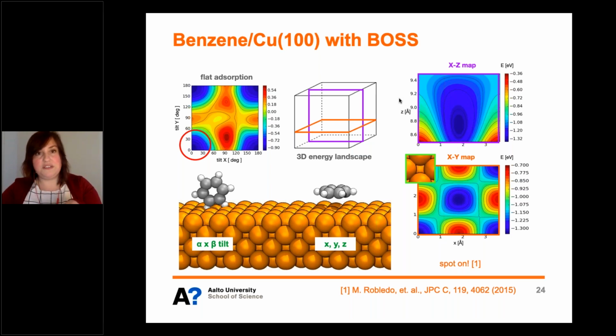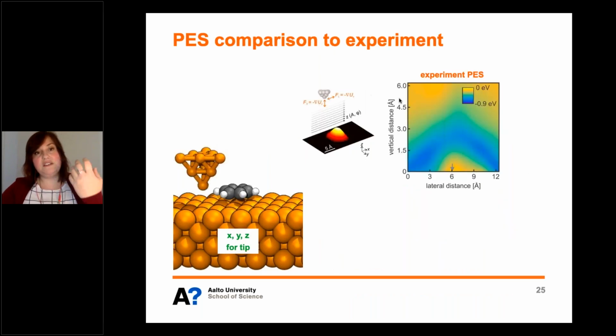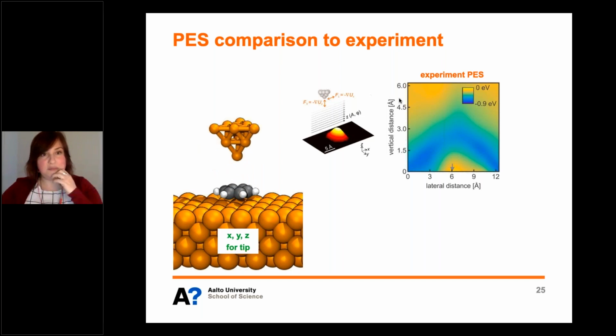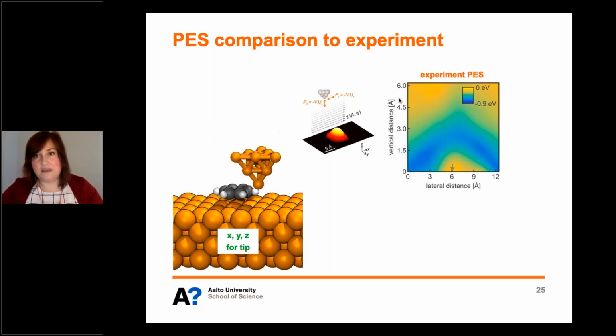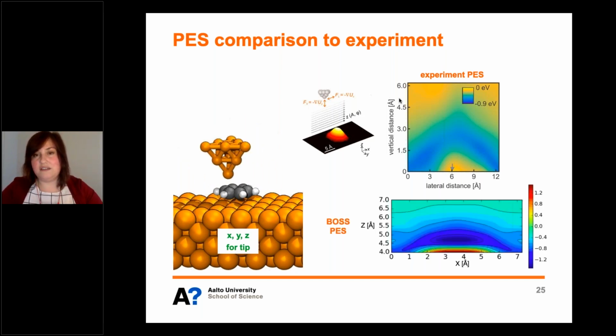So having learned about the adsorption of this system, we had to then introduce a tip, and we fixed the molecule, and we used the tip to sample the potential energy surface above this molecule. And this allowed us to build a 3D computed potential energy surface for the system. And when we sliced it in the same dimensions as the experimental measurements, we found a conical shape that looks similar. Here I compress it and overlay it for better comparison. So it looks pretty good. Our blue halo is also found at about minus 0.9 eV. And in the vacuum, we also go up to 0. So this is more than just qualitatively good, it's quantitatively good. We continued working with this group, and now we're helping them measure diffusion barriers on the surface.